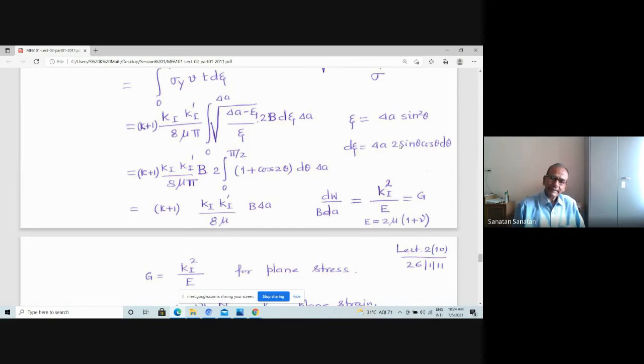It depends on the external loading and the crack geometry, and it is now also related to the fact that at the point of onset of crack extension, the energy release rate per unit crack extension is related to this parameter. So therefore, you see that Griffith theory of crack extension, associated with a critical quantum of energy release rate, is equivalent to saying that crack extension is associated with a critical stress strain field around the crack tip. It's not stress strain at a point, but it's a field.